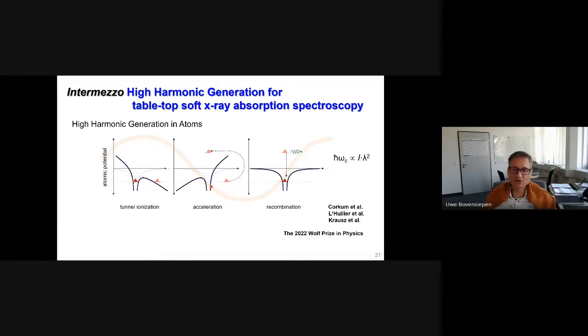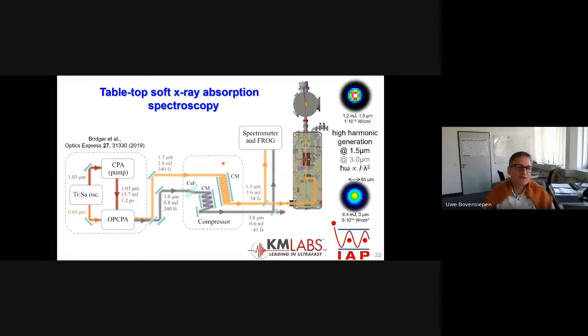But this can be understood such that you have acceleration over a longer time because of the longer wavelength, where the electron can pick up this energy out of the laser field. So we exploit this, and we need lasers that operate at infrared region. Remember, the Titanium Sapphire laser operates at 800 nanometer, but we want to go further out. And we have developed, therefore, an optical parametric chirped pulse amplifier, which is indicated here.